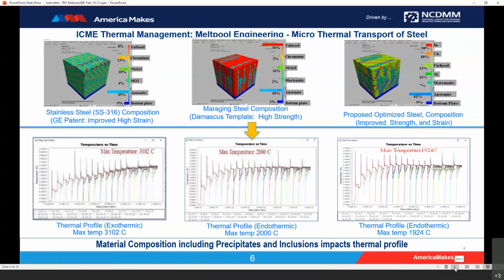as a consequence of the endothermic effect of martensite, which takes out all the heat and does not allow the cooled powders to join or fuse together. For the GE stainless, the percentage of unfused powder is almost zero. This is because of the exothermic effect of silicon oxide, which provides the heat to melt and fuse the powder. The uniqueness of this exothermic effect is free heat to be used in an engineering manner.